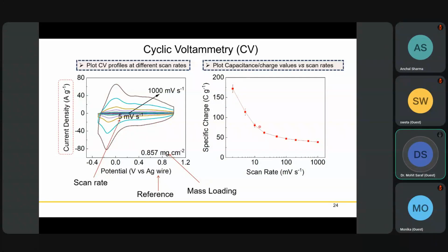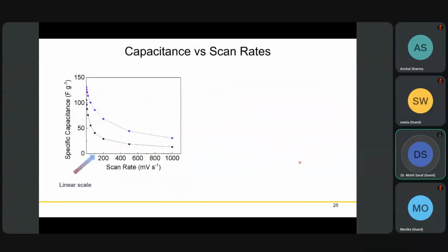When we increase the scan rate, you get less capacitance. Why? Because at higher scan rates, your electrolyte molecules are not able to access the inner spaces of your electrode. This is very general, the trend always goes like this. But it is very important to see that whenever you present your data, you always see that specific capacitance value goes down with increasing scan rate.